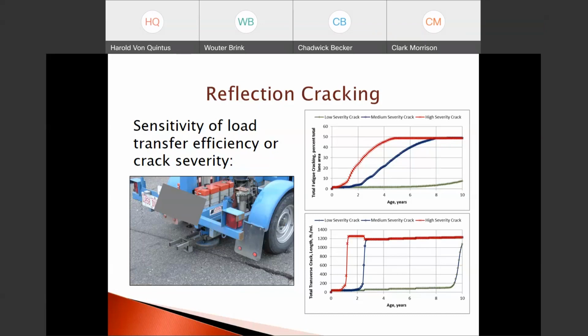And again, for 10 years. So crack severity for both fatigue and transverse cracks in the existing pavement are extremely important in terms of when those cracks are going to reflect through the overlay.